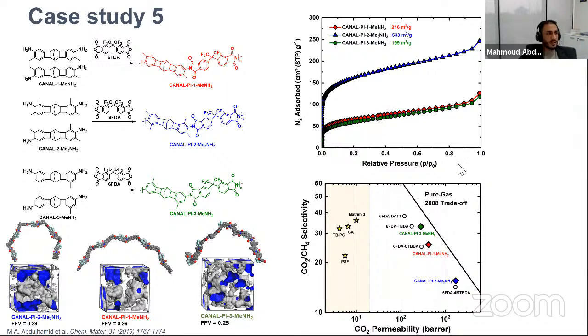Having said that, if we look at the performance of this material and compare it to the commercially available material, we can clearly see that the one that has two methyl groups next to the imide linkage is performing very high in terms of permeability, which is up to thousands. And when we go with fewer methyl groups next to the imide linkage, the permeability goes down, but the selectivity goes higher.